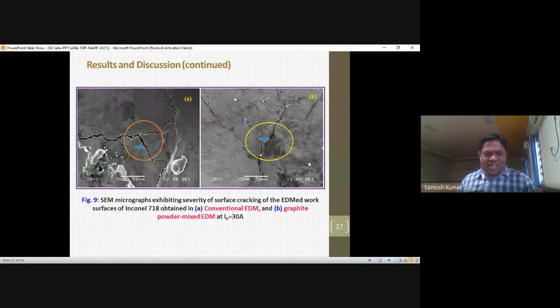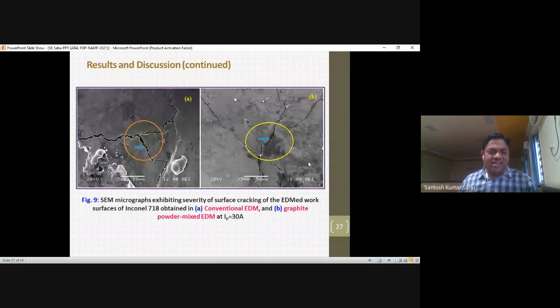That's why you have to see, in conventional EDM, what is the intensity of the cracks, and what is the intensity of the cracks after adding the graphite powder at a current of 30 amperes. See again, this analysis reveals that the machined surface produced by conventional EDM consisted of globules, debris, and surface cracks, and all that abundant white compound in these things should be removed in powder mix EDM.